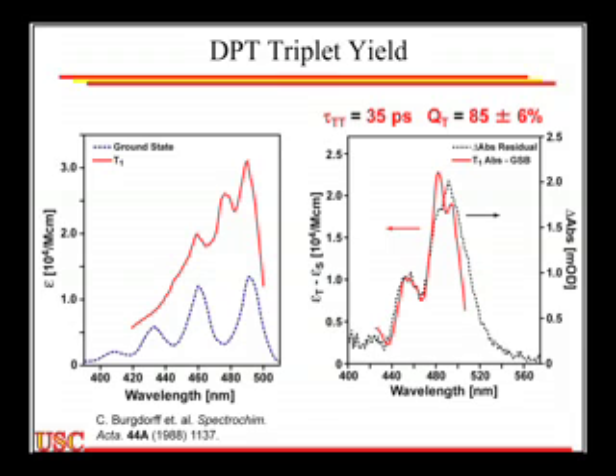It was not a singlet fission experiment. They simply put it in with the triplet sensitizer. And they measured the extinction coefficient for us, which made life really simple, because now I can take my transient absorption spectrum and calculate an efficiency, because I've got the extinction coefficient for the triplet. The yield is about 85%. So that means if I pump the platinum porphyrin, 85% yield ends up in the triplet on DPT.